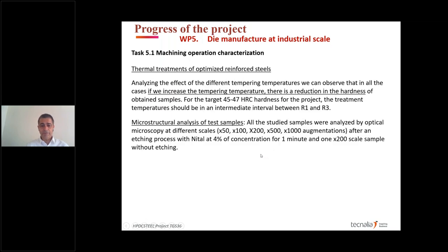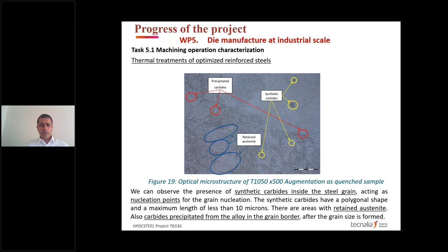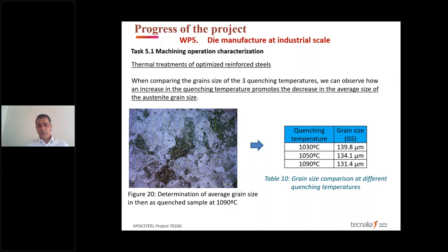So we define these treatments. After we analyze the temperature at 1050 degrees, we see the presence of precipitated carbides, and also synthetic carbides that are different. We see that the precipitated carbides are more on the grain boundaries, and the synthetic carbides are normally inside the grain, and some retained austenite was also discovered in this analysis.